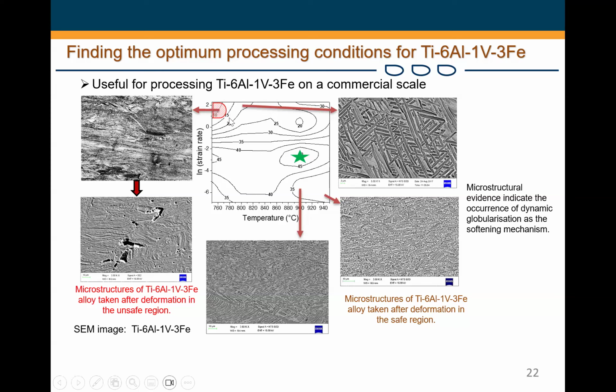But if you move away from this region, still very low temperature but high deformation speed, you're not seeing those rounded structures that we like. But as you increase the temperature and reduce the deformation speed a bit, you can begin to have those rounded structures, which is the globularized microstructure. If you test Ti-6Al-4V, the gold standard and the most utilized titanium alloy that we have in the world, under similar conditions, you would have this behavior. So we were able to establish that yes, we can reduce those 4 steps by just exploring